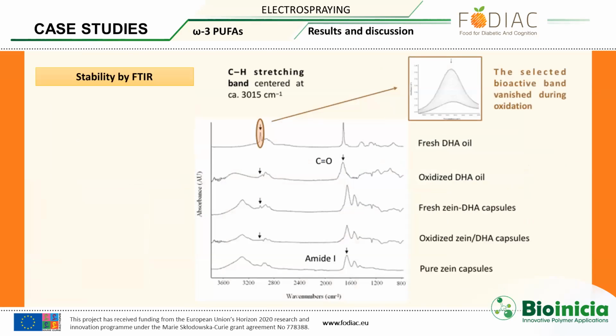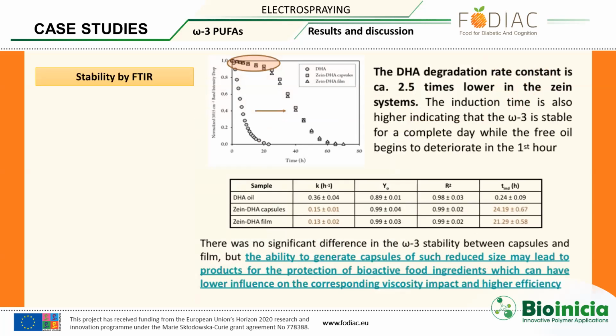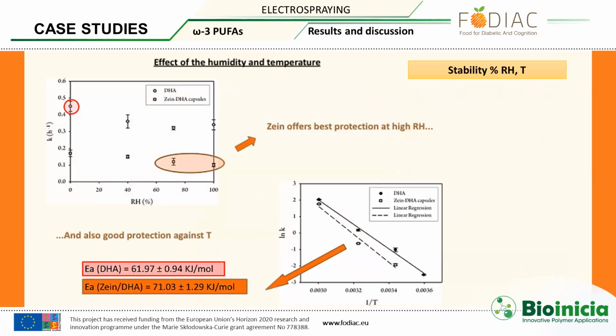We have followed the stability of those particles through FTIR, following the main functional groups, and we have observed that we can retard the degradation of the oil 2.5 times. As well, we have studied the stability to humidity and temperature, and we have observed that the capsules always provide a higher stability to the oil.